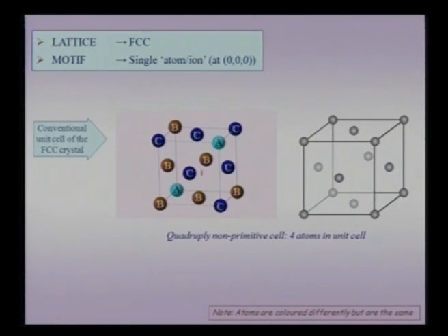Now the way of constructing is actually constructing along the vector connecting the A to the A atom, which is now my 1, 1, 1 direction. So the AA vector, the direction connecting my A to A, is the 1, 1, 1 direction, and I am trying to construct my crystal along that direction. So you can see that the A exists, then there is a B layer which is now made by these B spheres, then there is a C layer, and finally there is one more A layer.